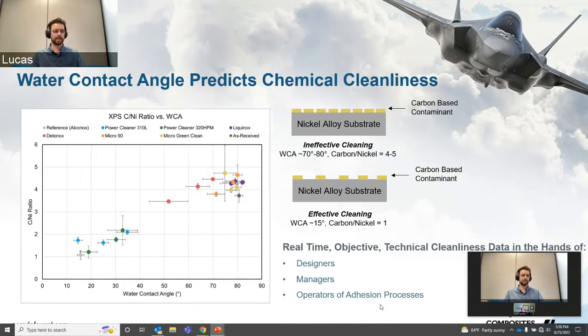We can get to a very objective measurement of metal cleanliness here by creating a carbon to nickel ratio in our XPS system, and we can correlate that directly to a water contact angle result. That carbon to nickel ratio is basically how much carbon signal we're getting in relation to nickel on that surface. You can see when I'm at an 80-degree contact angle on the right-hand side of the chart, I've got a very high carbon to nickel ratio. As I start cleaning this nickel through different techniques, my contact angle goes down, down, down, and my carbon to nickel ratio goes down. It's pretty darn close to a 45-degree line, right? It doesn't get much better than that.